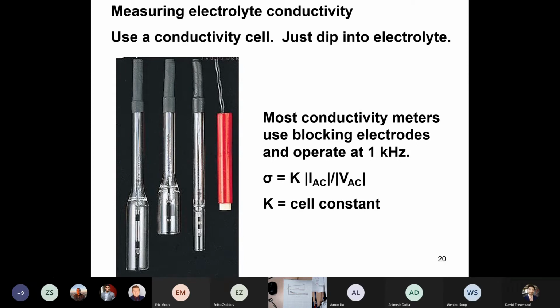So the first thing that you want to do is measure electrolyte conductivity. This is a very simple measurement. If you just imagine two flat plates of metal separated by a small spacing, 1 millimeter or 2 millimeters or something, and you just dip them into the electrolyte, you apply an AC voltage and measure the resulting AC current. That's proportional to the conductivity. So these are what conductivity cells look like, and they have the two metal plates, maybe you can see them here, dipped into the electrolyte. You apply the AC voltage, you measure the AC current. You know that's proportional to the conductivity, but you don't know what the proportionality constant is.